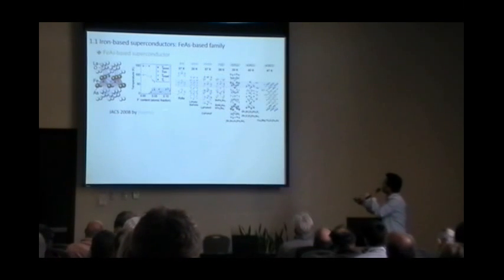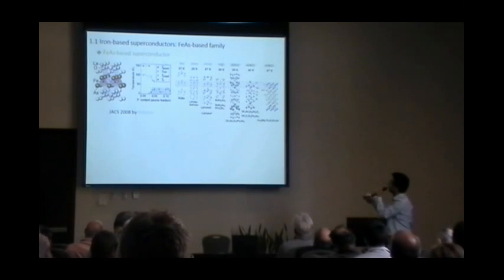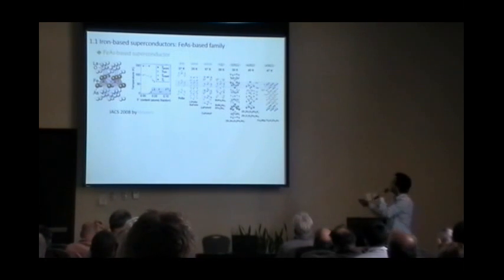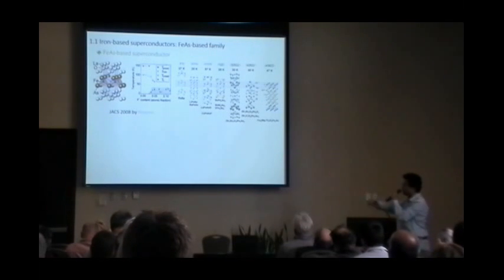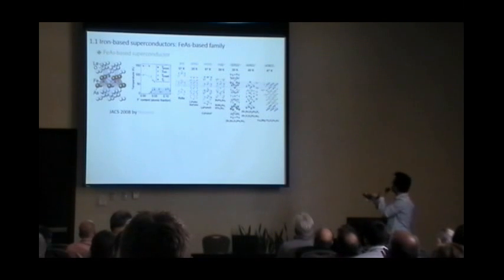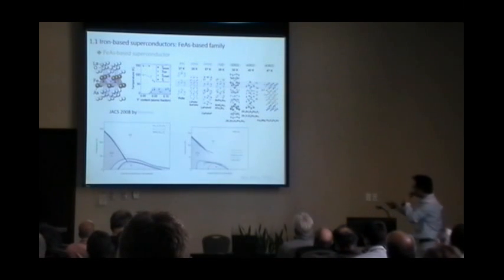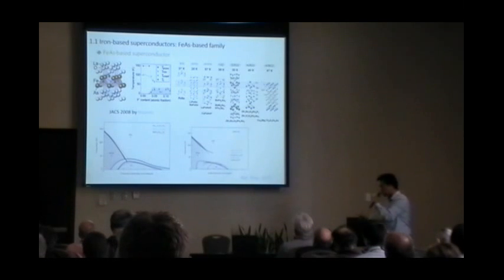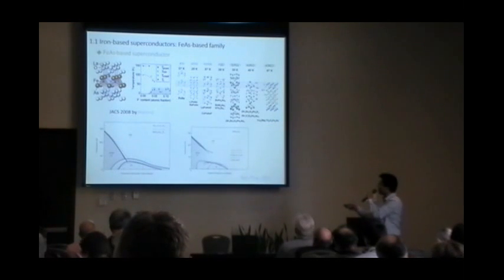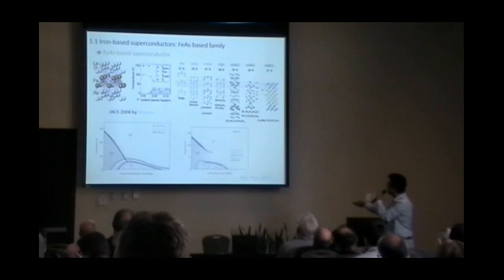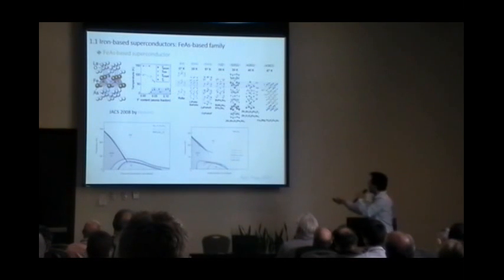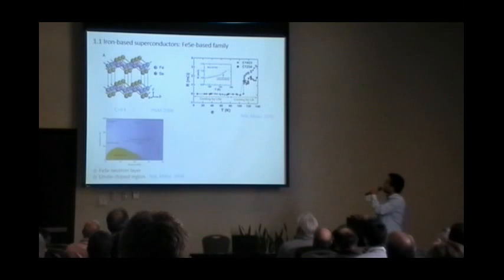One common feature is that they have the same layers showing here. This one is the so-called conducting layer. But the other layer, we can change a lot, from one element to these very complex layers. Another feature showing here is that once this iron-based compound is tuned by doping or pressure, the ground state is suppressed. There is a dome of superconductivity showing here.